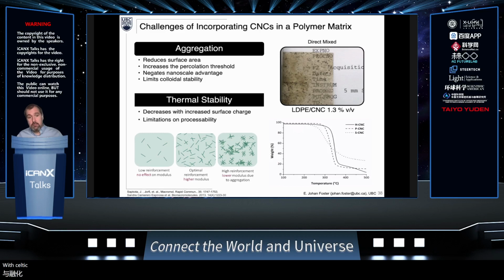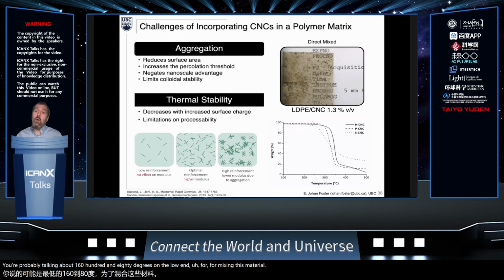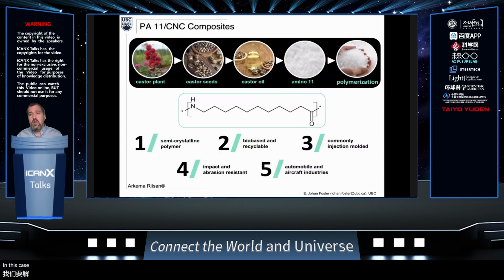With melt extrusion, by its very nature, you need to melt that material to get it to mix. So in the case of polyethylene, you're probably talking about 160, 180 degrees on the low end for mixing this material. For other polymers, like the polyamides, you need to be at 250, 270 degrees Celsius to be able to mix these. So the thermal stability of your polymer is okay, but the thermal stability of your cellulose, your filler, is hugely problematic. Okay, so ours starts to turn brown or turn black, and you don't get the reinforcement. So we want to solve this. In this case, we're going to use PA11, so polyamide 11, structure in the center there.